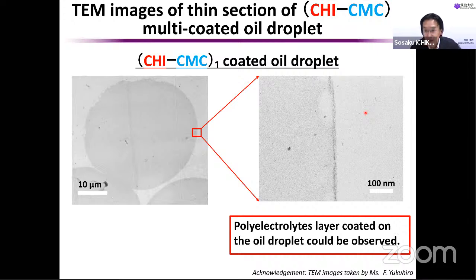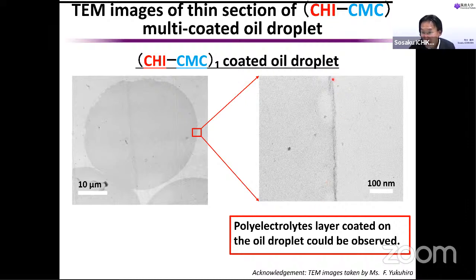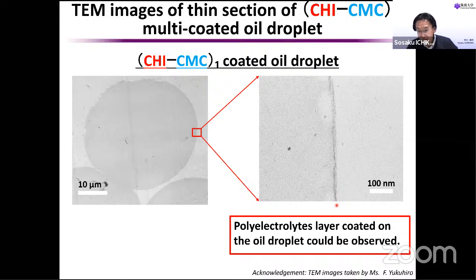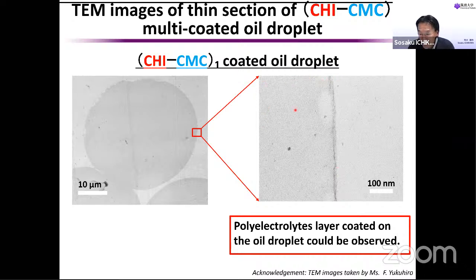We also observe the layer on the oil droplet by electron microscopy. This is the TEM image, the electron microscopic image of an oil droplet. You can see the size is relatively large. So when we enlarge this surface, we can observe this kind of layer. I think this is the polyelectrolyte layer coated on this oil droplet. In this case, just two layers. It means the chitosan and CMC.